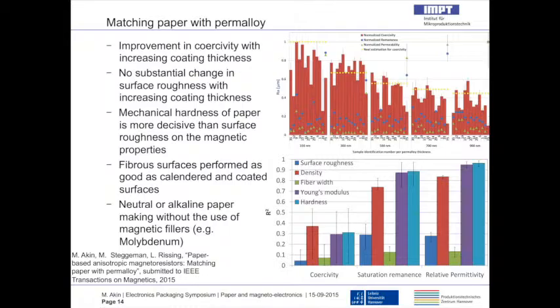What we also found out is that paper surfaces that are fibrous, where you see the fiber really visibly, compared to a paper that's been smoothened, calendared, or compacted, those papers perform as good as each other. That's an indication that, from what I said earlier and what we found in literature, the fibrous network is helpful for the magnetization process, for the motion of domain walls, basically lowering the coercivity.